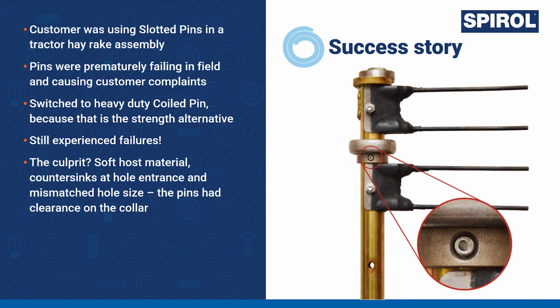And in each instance, we found that the hole in which the pin was used was elongated. All of the pins that failed in the hay rake assembly, the slotted spring pin, the heavy-duty coiled spring pin, and the heat-treated solid pin, were actually too stiff for the soft material. The result was that as force was applied on the pin, none of these pins were flexible enough to absorb the shock and vibration, and the pin simply transmitted the force onto the hole wall, and that resulted in deformation. And once the hole was elongated, any force on the pin was exacerbated due to the movement of the pin within the widened hole on force reversals.